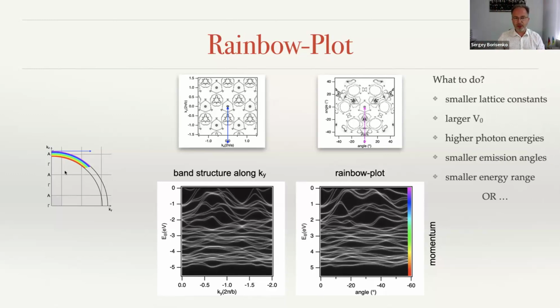One could look at this plot here and take materials with smaller lattice constants. The smaller the lattice constant, the larger the Brillouin zone, and the larger the Brillouin zone, the less of it we cover. One could find materials with larger inner potential. It happens that for some materials V0 can vary from 5 to 20, as far as I know. One could go to higher photon energies in order to increase the radius of the emission sphere, and then it would be kind of tangential to the emission sphere. One could live with this, but then one loses energy and momentum resolution.